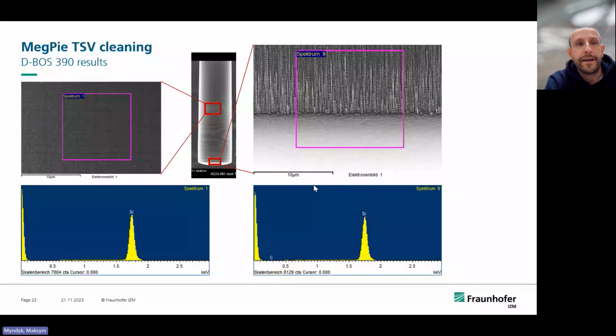We also did the EDX analysis of TSV cleaning by MegPie technology. What do we see here? In the places where no residual is visible, there are no fluor signals at all. So this means that the walls and the bottom of the TSV are really clean. So it was the first try with this chemistry, and with the TSV 260 to 80 micrometers.